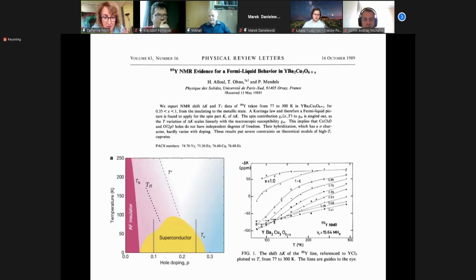Okay, so here is the infamous phase diagram of the cuprates. When we look at the phase diagram, we see three things. This is copper oxides, and it's an insulator at low doping. This is doping in oxygen. Then it starts to superconduct at very high temperature. And in between, we have this phase that we will talk about a lot, which is the pseudogap phase.